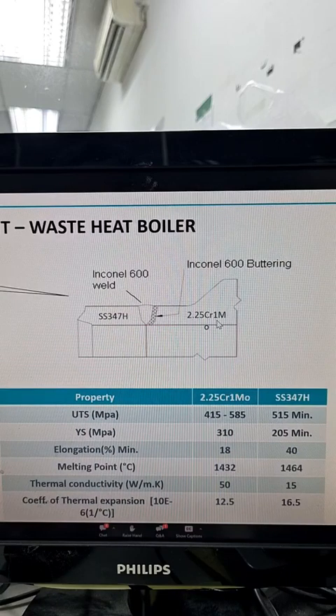Again you have 2 1/4 chrome 1 moly on one side which is joined to SS347H. Generally you do it with an Inconel buttering, subjecting the 2 1/4 chrome to PWHT, and again join with Inconel 600.